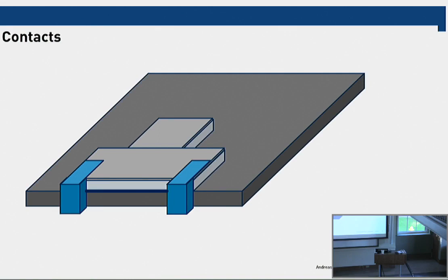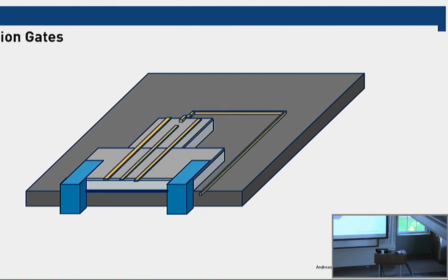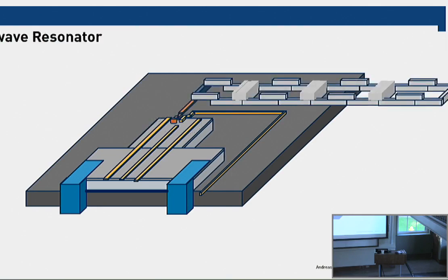So we remove the two-dimensional electron gas almost everywhere. Then we put these ohmic contacts into the electron gas that allow us to inject electrons from the top of the chip into this two-dimensional electron gas layer. Then we pattern metallic leads on top of that structure that we can then bias with voltages. And if you choose the right geometry and apply the right voltages, you can make two puddles of electrons in these regions, for example. And so we form our double quantum dot here,